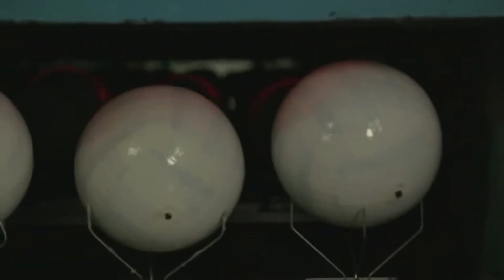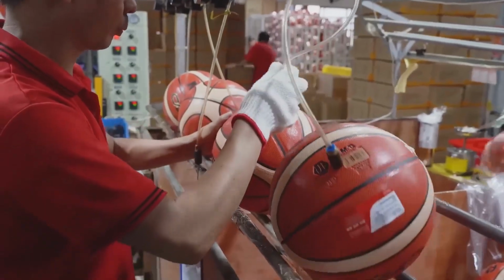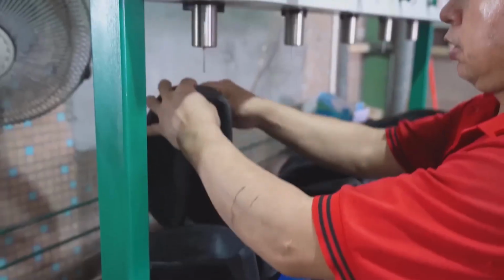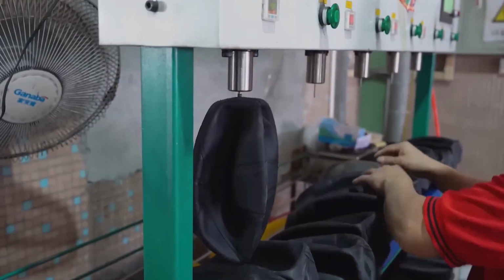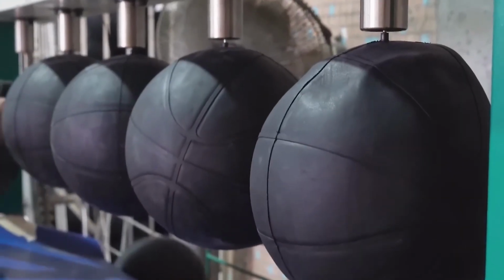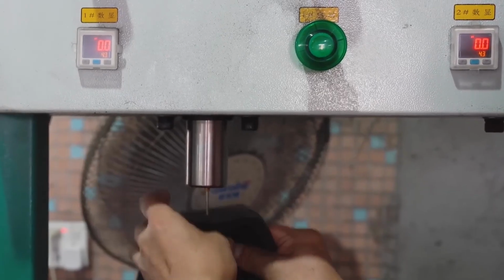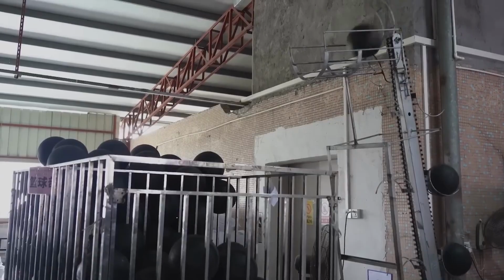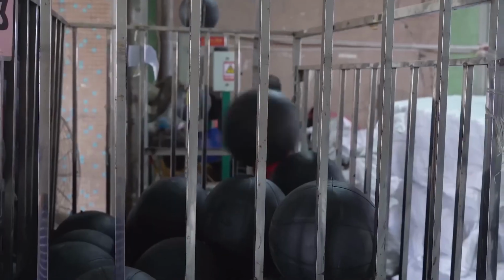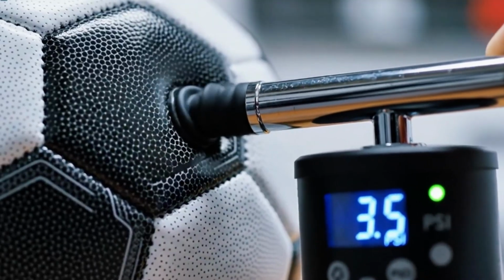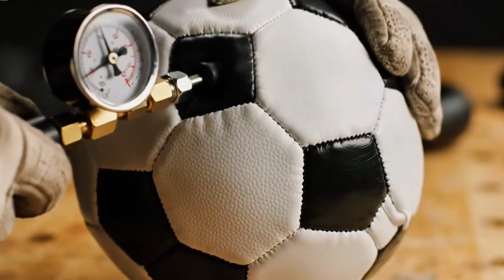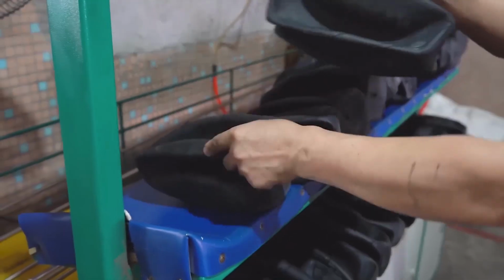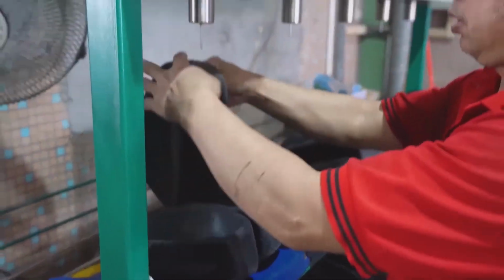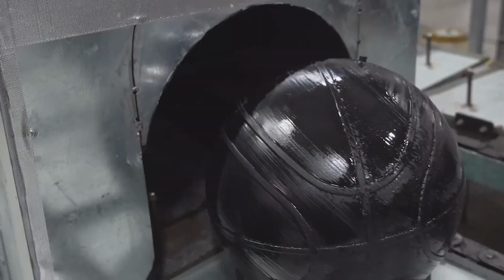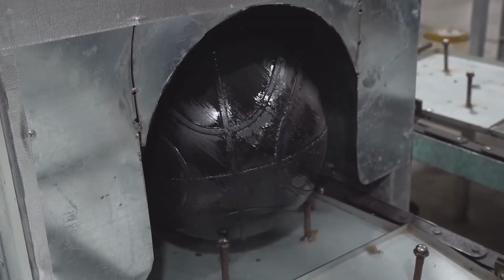The bladder, the heart of the ball. Inside every quality soccer ball sits a bladder that holds air pressure and maintains shape. Bladders are manufactured from latex or butyl rubber, with each material offering distinct advantages. Latex bladders provide superior responsiveness and a softer feel but require more frequent inflation. Butyl bladders retain air pressure longer, but offer slightly less responsiveness. The bladder manufacturing process involves extruding rubber into thin sheets, cutting them to shape, and vulcanizing them into seamless spheres.